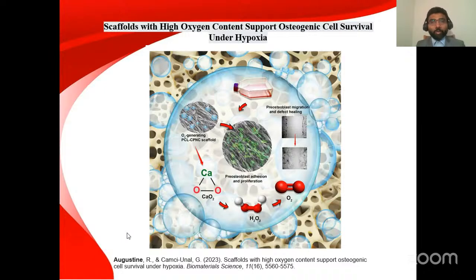So we thought how incorporating oxygen generating materials can help to overcome such a challenge. So we developed oxygen generating nanomaterials to incorporate into tissue engineering scaffolds to improve bone regeneration. Here we synthesized calcium peroxide nanoparticles, calcium peroxide nanocuboids, which have a cube-like structure. This material can generate oxygen. First they produce hydrogen peroxide, then it will be converted into oxygen in the presence of catalase in the body.